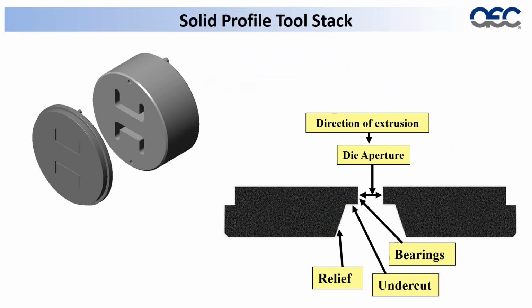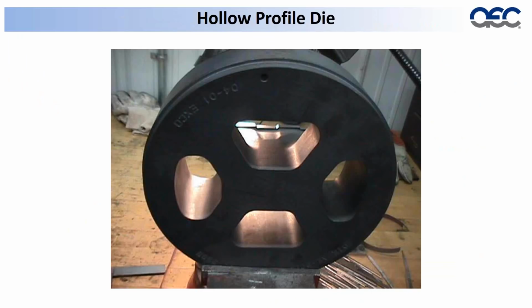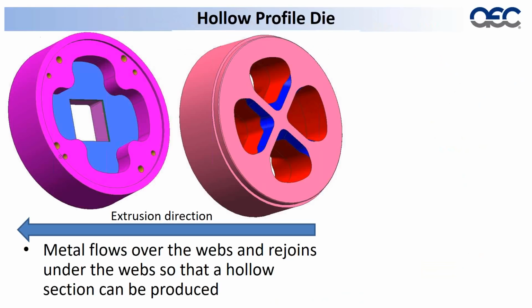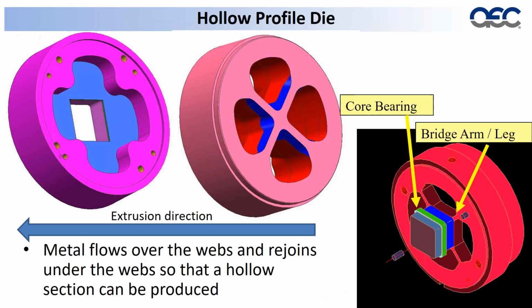When you look at hollow profiles, the dies become much more complex, as in it's a three-step operation. The material must go through the ports. It goes down along what we call bridges, which suspend the mandrel. The material actually meets together in a welding chamber prior to the aperture. It adheres to itself, and then it extrudes out over the mandrel that's suspended and the die plate which forms the outside portion of the shape, both sides having bearing, and then it extrudes out and you end up with a hollow section, with the open part in the center being relatively any configuration you want, but it does take a slower extrusion speed and a lot more pressure.